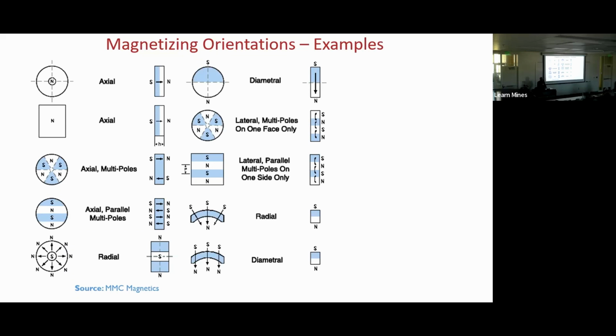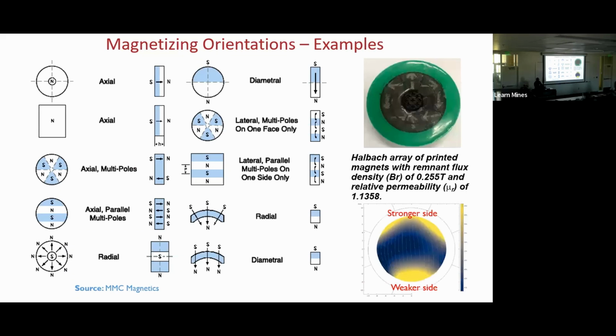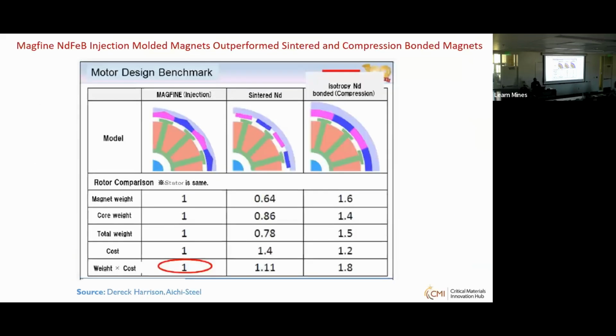So every magnet, it doesn't matter, either it's sintered or it has to go through this magnetization procedure. Or you can make this Halbach array we talked about. So this is using some other printed magnet. You can see the magnetized direction is shifted by like 90 degrees and you can make the whole thing. So you can actually make a magnet with either a strong side or a weaker side. So you can play with this magnetization field and you can do all those things.